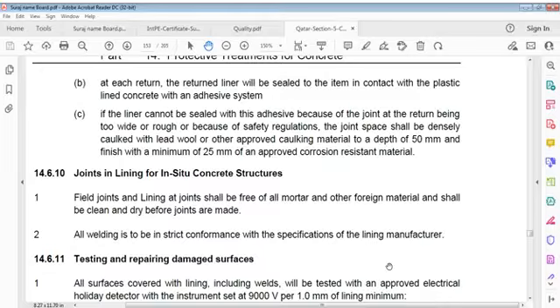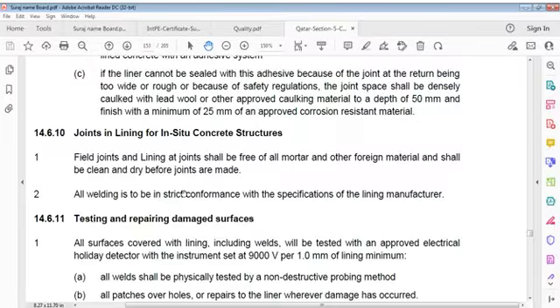Now, joints in lining for in situ concrete structures. If liner cannot be sealed with adhesive because of the joint at the return being too wide or rough, or because of safety regulations, the joint space shall be densely caulked with lead wool or other approved caulking material to a depth of 50 mm and finished with a minimum of 25 mm of approved corrosion resistant material.